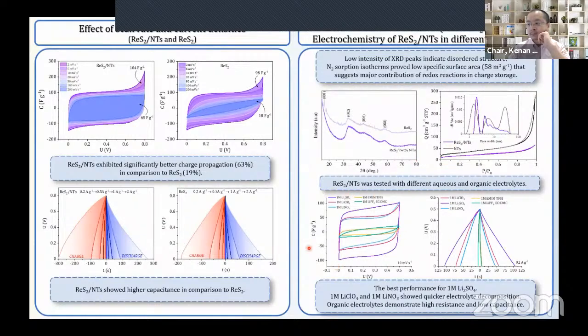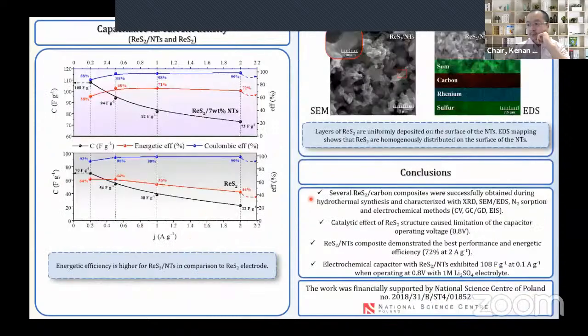Later we have decided to compare this material in different electrolytes, and it occurs that the best performance was reached for 1 molar lithium sulfate. Here you can see that not only the capacitance was improved, but also the energy efficiency for this material was improved by about 30%. SEM and EDS images show that the layers of ReS2 are homogeneously distributed on the surface of the nanotubes.